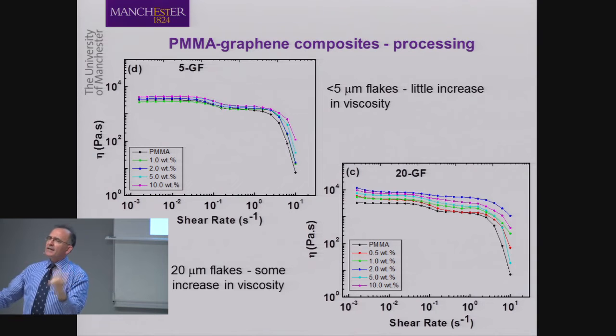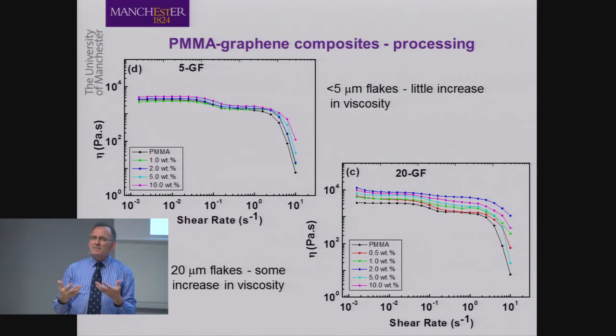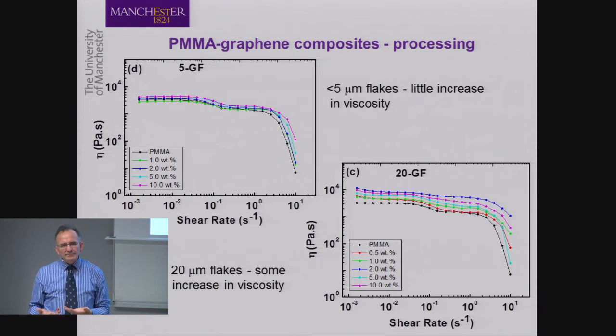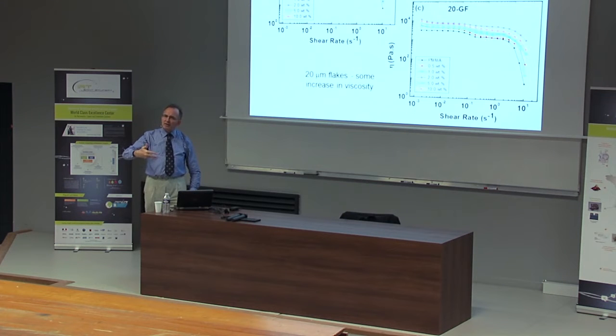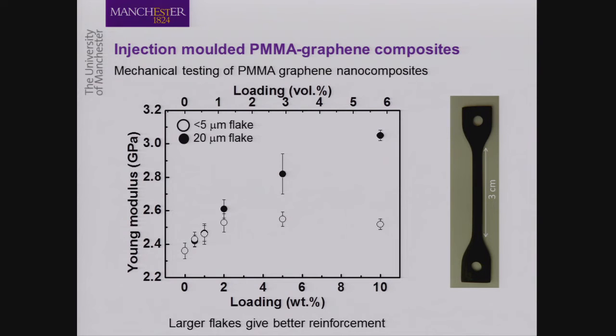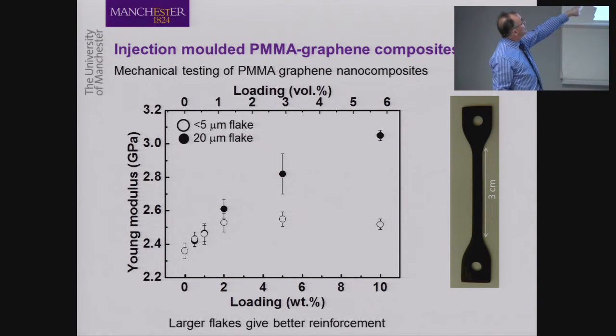And then if your thermoplastic is reinforced with continuous fibers, then maybe the benefit that you will get from graphene is not really felt as much. So these are critical issues on how we can mix and disperse uniformly the graphene in our matrix. And if we look at the Young's modulus, we can see that from 2.4 gigapascals, we have increased it. In percentage terms, it's a very high increase, but in actual terms, again, what am I going to do with 3 gigapascals stiffness? Maybe some people in the electronics industry or some other sectors are going to say, oh, this is a very significant increase, and I will benefit from that. But from the aerospace application, I cannot build anything with that.